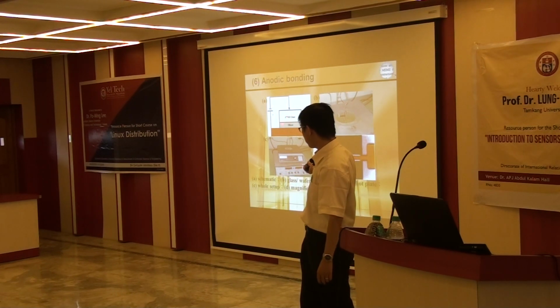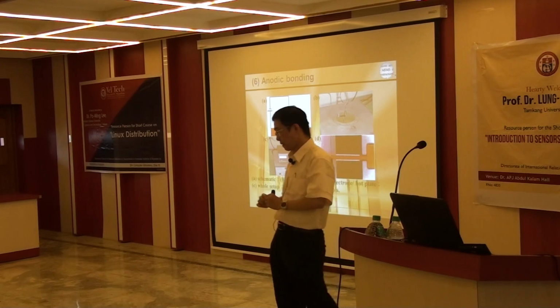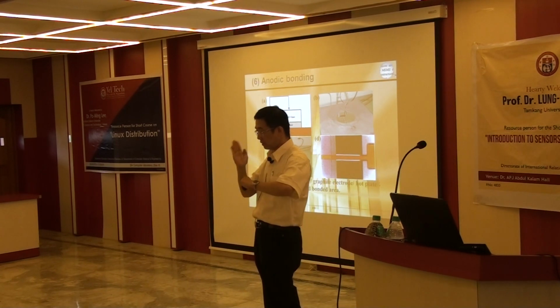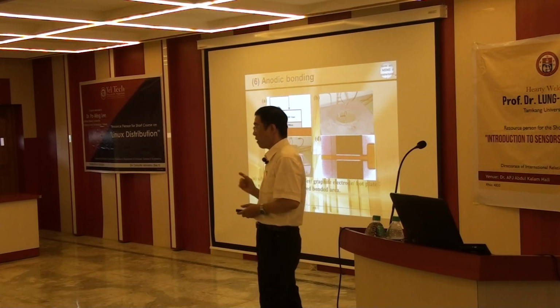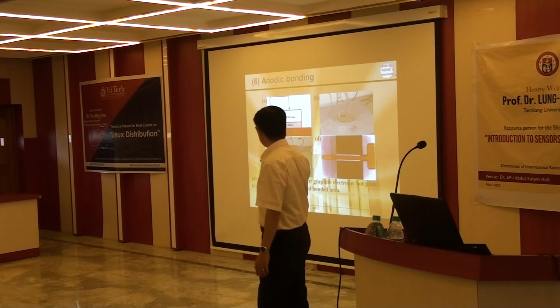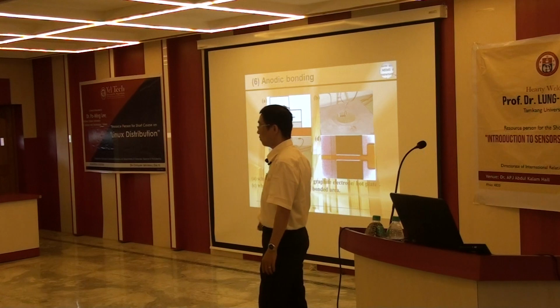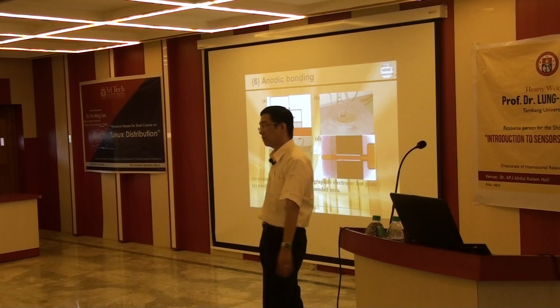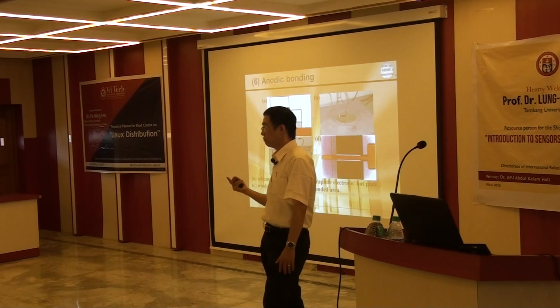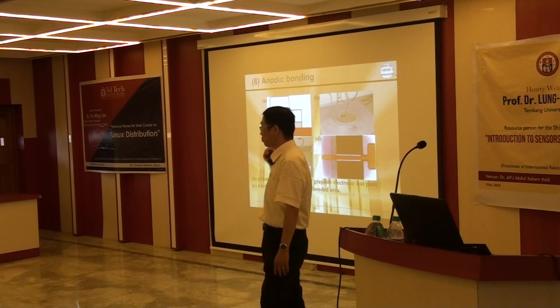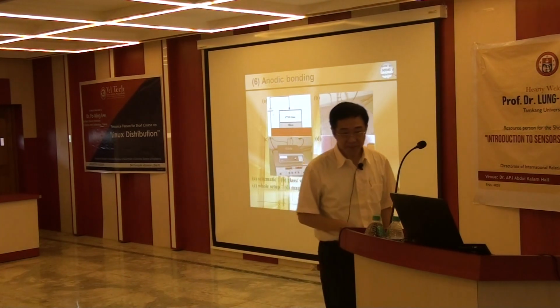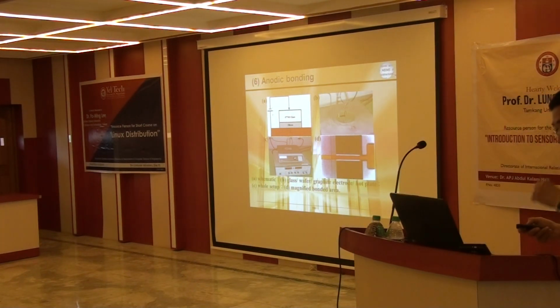To test the bonding strength, we try to peel it apart. After bonding, we use a weight to try to separate. Very hard. Finally, we found it broke, either the glass broke or the silicon broke, but the interface is still fine. So it means the bonding strength of the interface is larger than the fracture limit of this kind of material, very, very strong. So anodic bonding is very easy to make, but useful. Not only for the MEMS sensor package, it may also be useful for other applications.